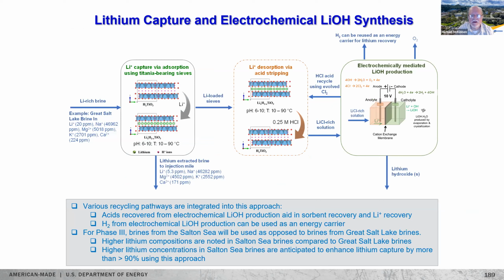So here's a schematic showing the lithium adsorption step on the left, the lithium elution step in the middle, and the electrodialysis step to produce lithium hydroxide from lithium chloride on the right. So far, we have tested our lithium extraction process with the hydrogen titanium trioxide absorbent using Great Salt Lake brines with 20 ppm of lithium in them.